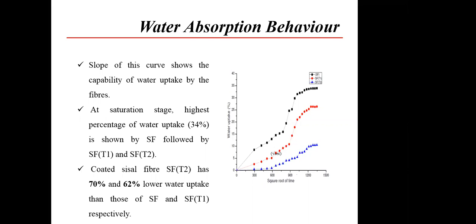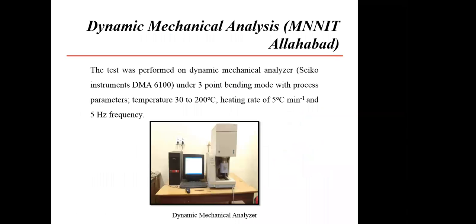But if we talk about the treated and coated fiber, there is 70 and 62% lower water uptake by the fibers after treatment. These are good, positive results obtained after the treatment. If water uptake is less, that means the strength and interfacial bonding are also enhanced. Now I am going to discuss the dynamic mechanical analysis.